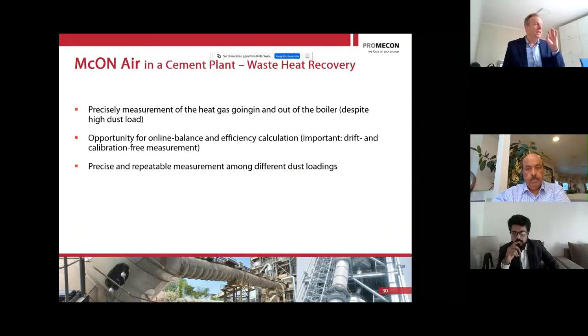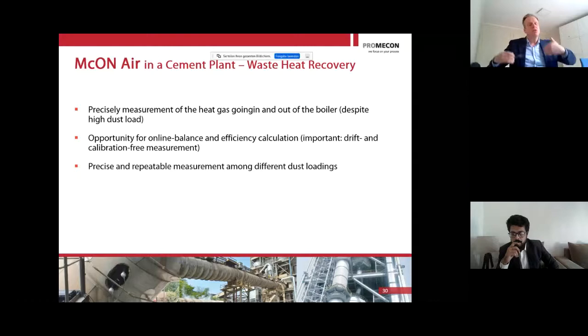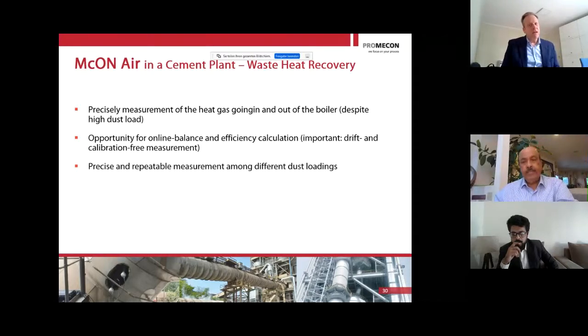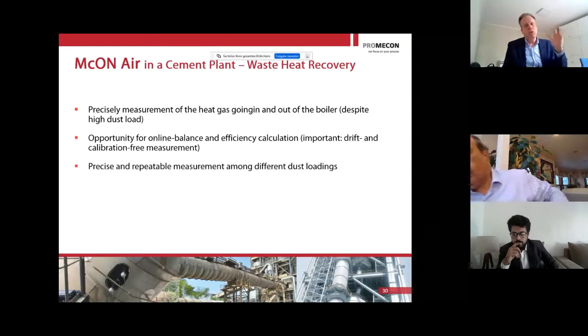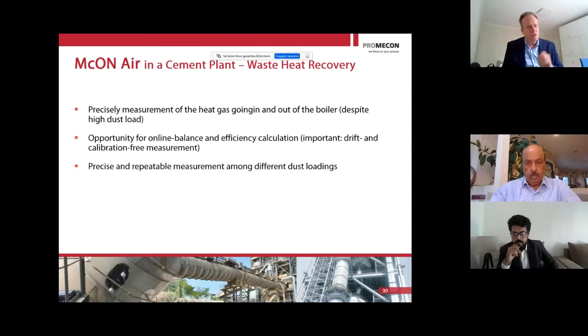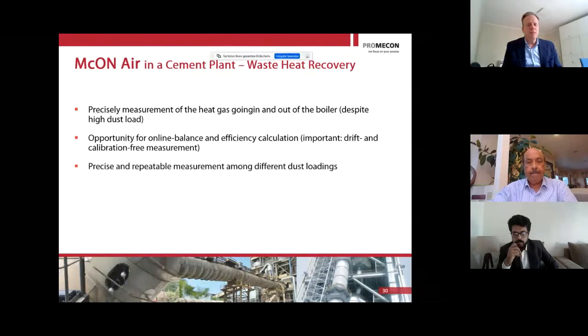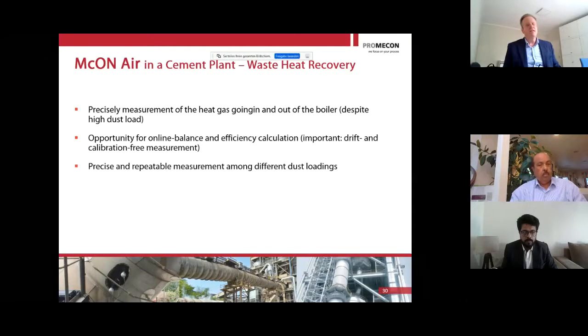So precisely to measure the hot gas going out of the boiler also allows you to have a better calculation of your efficiency. You would like to know, when you have a waste heat recovery boiler downstream the clinker cooler, how much enthalpy am I putting into my waste heat recovery boiler? You would like to measure the enthalpy flow. Now, I'm sure you have good temperature measurements on those pipes, but I bet you do not have any good flow measurement. So how can you calculate the enthalpy into your waste heat recovery boiler when you have no flow? You have to have flow. This is the key element. So this is what we're giving you. We're giving you an accurate and reliable flow measurement on your waste heat recovery boiler inlet.